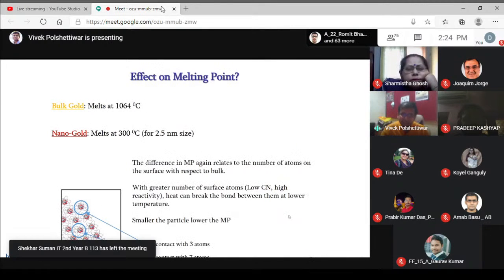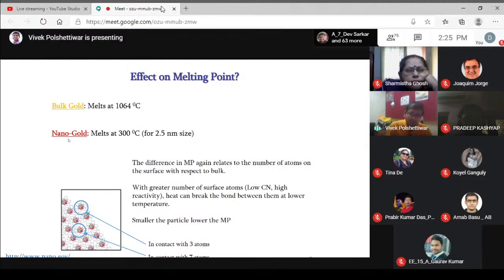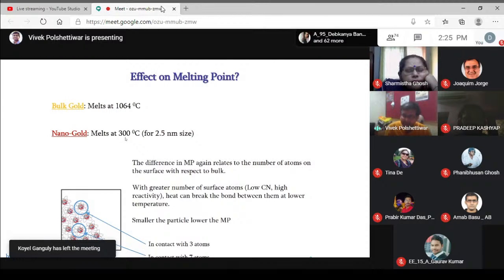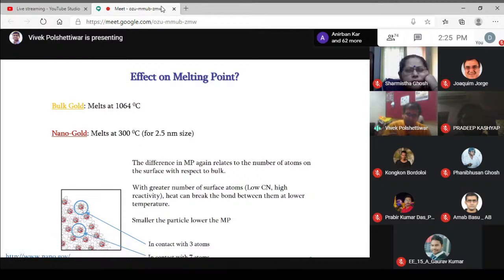Another example is melting point, right? If you again take the example of gold, it melts around 1064 degrees Celsius, but if you make a nano gold of around 2.5 nanometer size, you see it starts melting at 300 degrees Celsius, a dramatic decrease in the melting point from 1064 to 300 degrees Celsius. And if you look at this small cartoon, you will see that when you have a bulk gold, you have a less number of surface atoms and more number of bulk atoms. Whereas when you go to the nanoscale, you have more and more atoms on the surface, right? Because of the smaller size and higher surface area, surface energy.